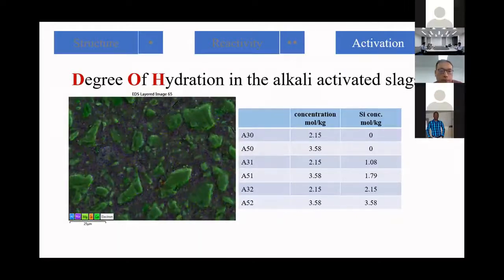In this section, I will give just the alkali activation mechanism of slag, because as introduced before, slag is much simpler than fly ash. So in this part only slag is discussed. Firstly, I look at the degree of hydration of these alkali activated slags in different activation conditions, using different alkali concentrations and also silicate concentrations. It's denoted by two numbers. The first number is the weight percent, or the concentration, of the alkali. The second number denotes the silicate modulus. For 0, it means that there's no silicate from the activator.